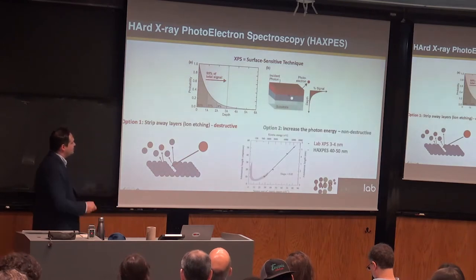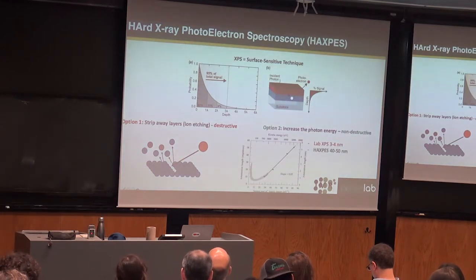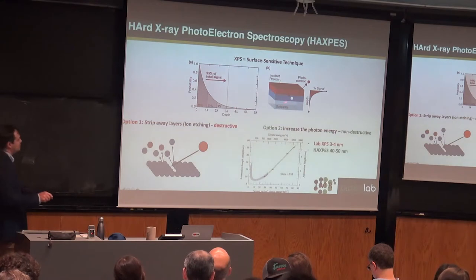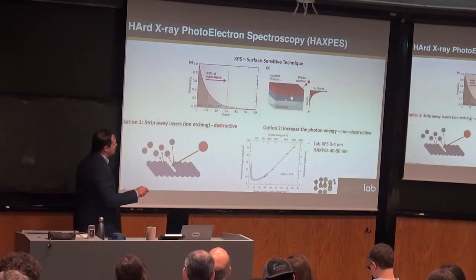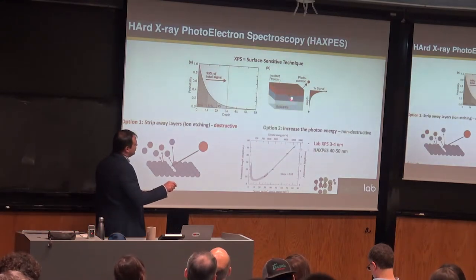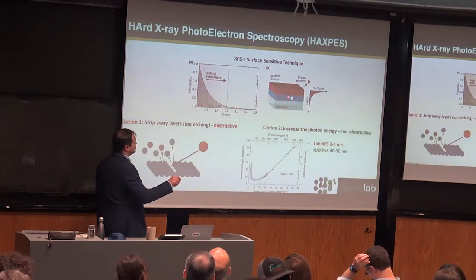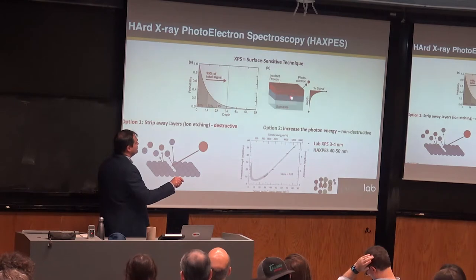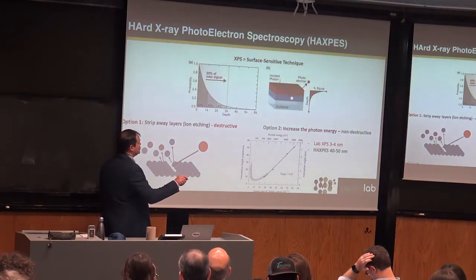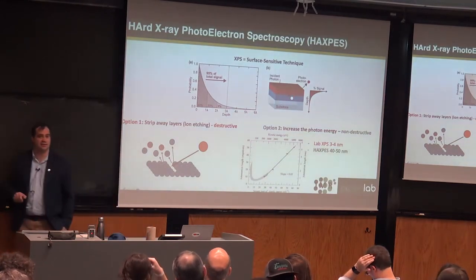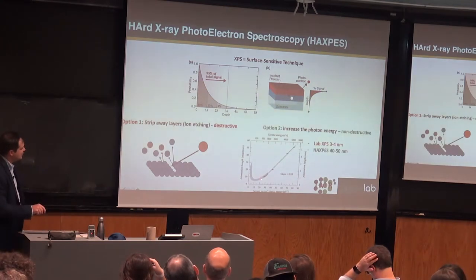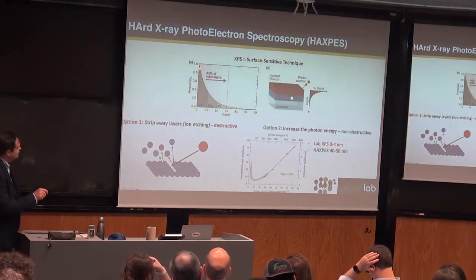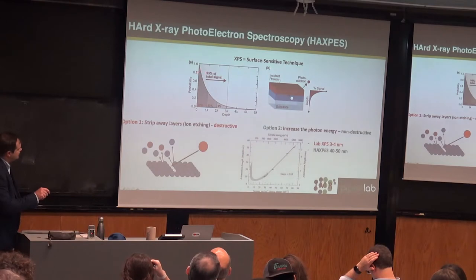So the other approach is to increase the photon energy and go up the universal curve. So the idea is, for the same core hole binding energy, you are transferring more kinetic energy and momentum, giving the electron more chance to escape without losing its energy. And that does mean that you gain quite a lot because you increase the attenuation profile.